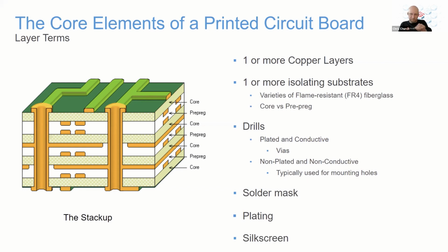Because it's very, very flat. So if you think about the hot air solder leveling, it's just a bunch of solder on there, and there can be ripples and waves, and that can cause components to sit at odd angles, which for many of the larger components we're working with isn't a big deal. But when you're dealing with a leadless package like a QFN or with a BGA, that lack of leveling can create manufacturing defects. And then finally, there's just your silkscreen.